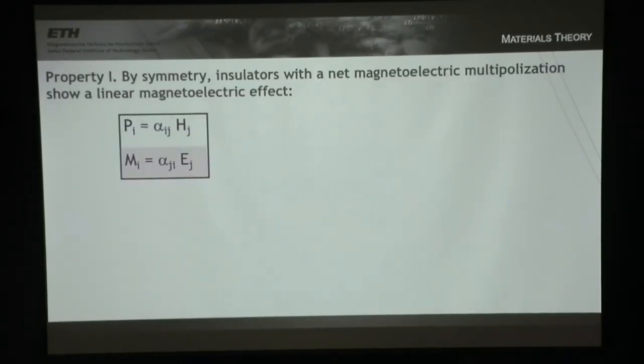So whenever I have a material with such a net magnetoelectric multipolization, then by symmetry, I have a linear magnetoelectric effect, which means if I apply a magnetic field, I induce an electric polarization, or if I apply an electric field, I induce a magnetization. And the induced quantity is linear in the applied field. Okay. So this is quite unusual, maybe even a little bit remarkable, right?